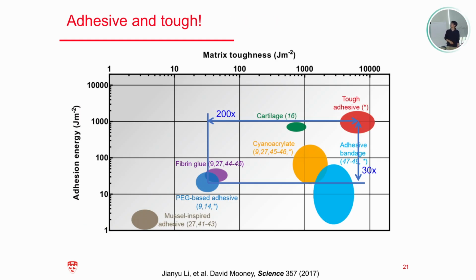And here is a summary slide of the performance. That is the focus of our mechanical design. We want to improve the adhesion energy and, at the same time, the matrix toughness. And luckily, these two quantities have a good synergistic effect, enabling each other. So in this case, you can see this nice effect in our tough adhesive. Compared to the clinically used glue, we are much higher in both quantities.